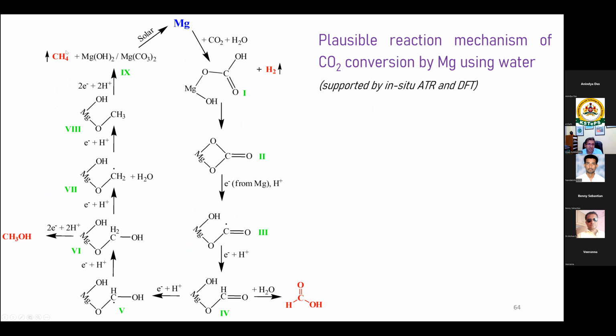Now the drawback is that although this entire thing is catalytic in principle, magnesium also reacts with water and forms magnesium hydroxide, and then CO2 reacts with the magnesium hydroxide to form magnesium basic carbonate. So at the end of the reaction, all the magnesium is used up for this magnesium basic carbonate formation. So overall, the reaction is no more catalytic because the magnesium is no longer there, it's converted.